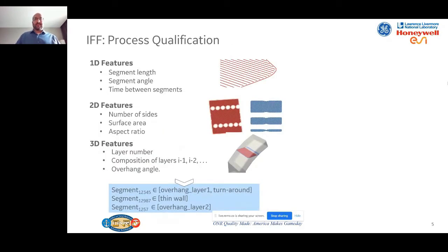Now, when we look at this type of technology, this type of control methodology on the machine, there's a lot of things we can look at here. 1D features, like what direction are the scan strikes going into? 2D features, so more of area-based understandings of wall thicknesses. Are we entering a corner of a part or not? And then 3D features, the level of an overhang, the height that you are into a part, how far away from the build plate are you? And for every laser strike, you could potentially have many different types of features that are associated to that one laser strike. You could have an overhang region that's also a corner. You can have a tall section of a part that's also a very thin wall. And so it's important for us to understand all these types of variations and use IFF to allow ourselves to accommodate changes where we find it's actually important.